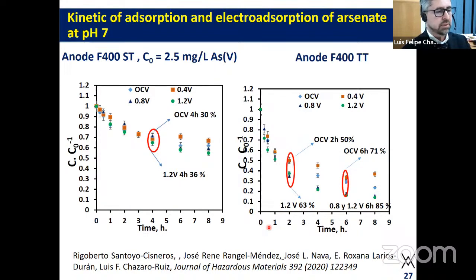Here in this slide, when the pristine material and the material with the heat treatment were used as anodes, this is the pristine and this is the material with a more reduction degree. And the material with the highest degree of reduction increased the rate and the capacity of the arsenate adsorption compared to the pristine material. And what we have to pay attention to is that at 0.4 volts, the electroadsorption capacity of the material at equilibrium was lower than when the material was not subjected to an electrical stimulus, which is called OCV in this case.